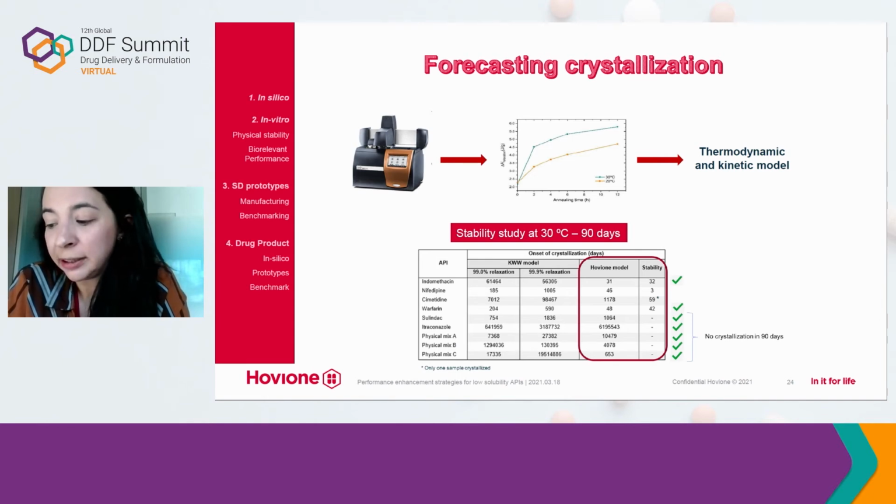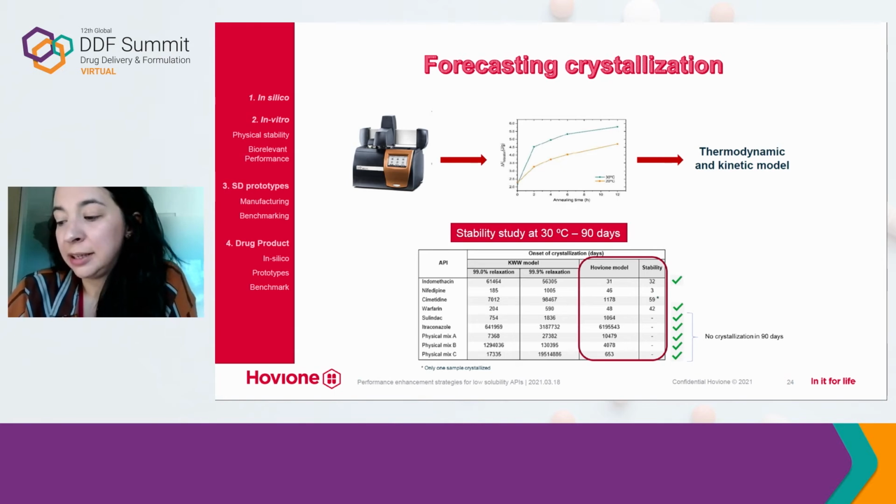At Hovione, a proprietary method for predicting the onset of crystallization of amorphous materials has also been developed. This mathematical model incorporates information on the kinetics of relaxation of amorphous materials at a defined temperature, not typically the temperature expected for the storage conditions of the material, and thermodynamic parameters that cannot be disclosed. The model is based on real data gathered from a couple of simple DSC runs.